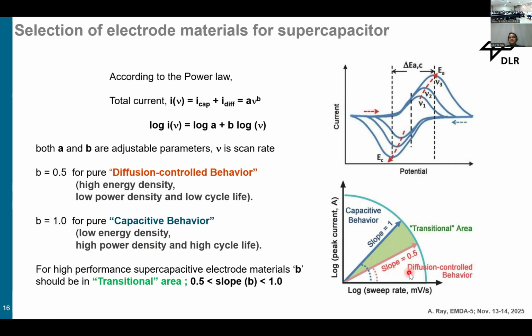But nowadays the current research on electrode materials is to develop some material in this range. That means it gives both capacitive contribution and redox reaction contribution. So for our new material, the b value should be in the range of 0.5 to 1. This is the transitional area. Whatever papers or research you look at, all are trying to get a new material composition with a b value in this range.